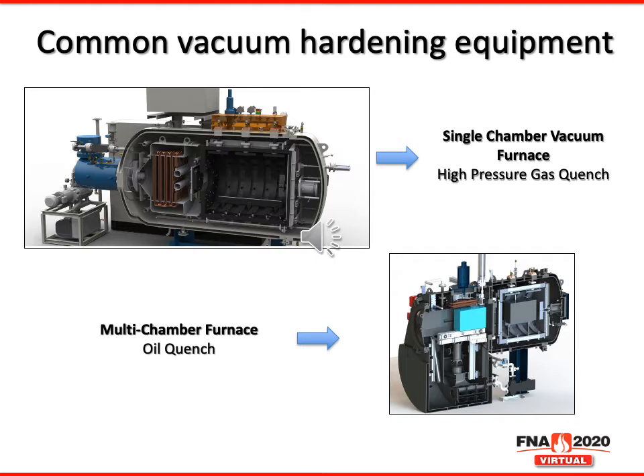There are two types of vacuum furnaces that are used for hardening. One is a single chamber vacuum furnace using high pressure gas quench. Now typically the part is placed in the heating chamber where it goes through a heating process, then is quenched using a gas media like nitrogen in that same position. Then we also have a multi-chamber furnace. Many times these are oil quenching furnaces, but they don't have to be. They could be a gas quenching furnace too. The one shown is oil.